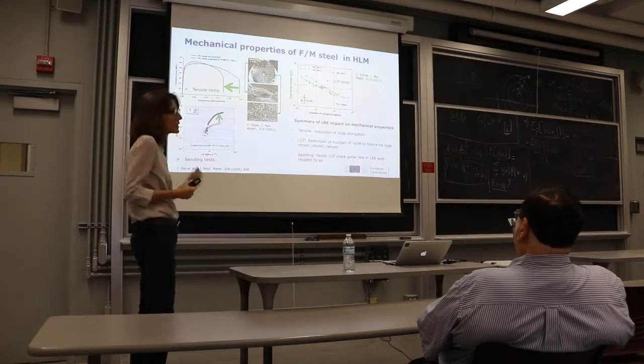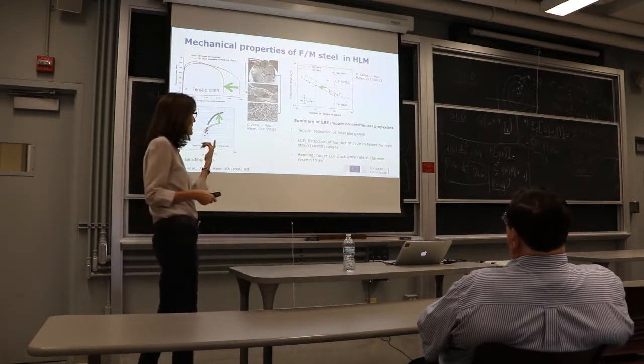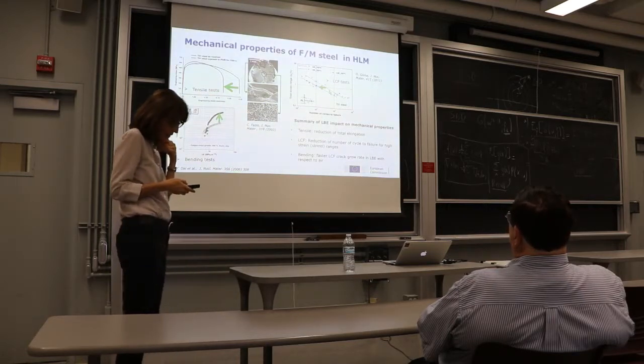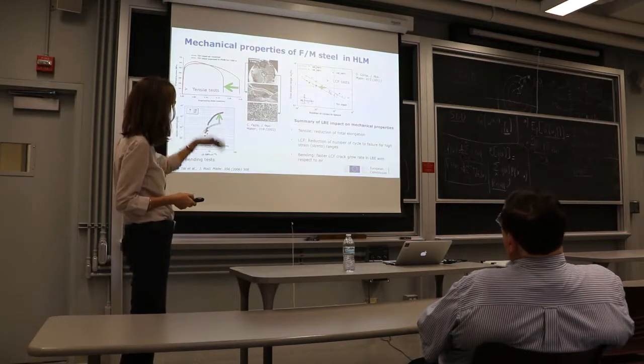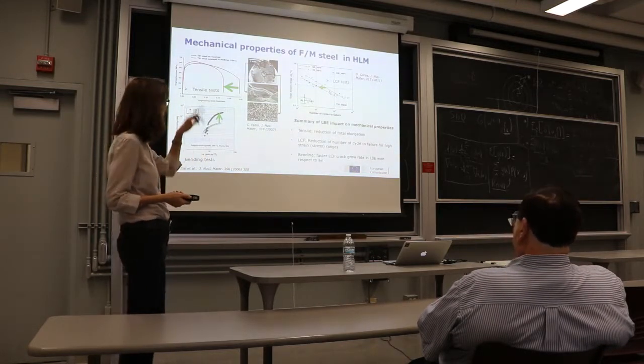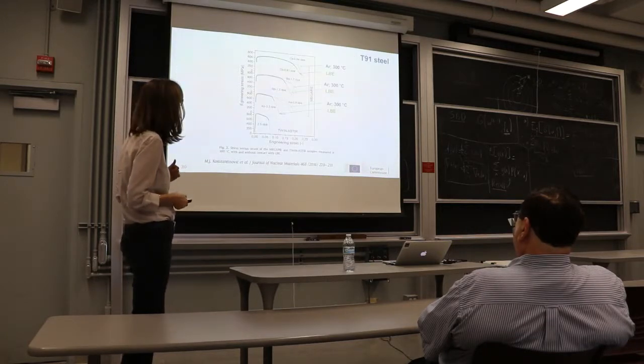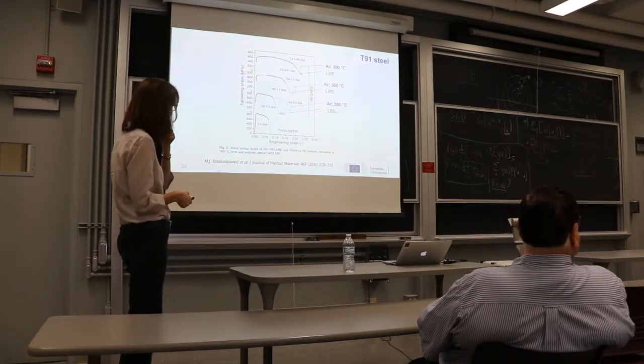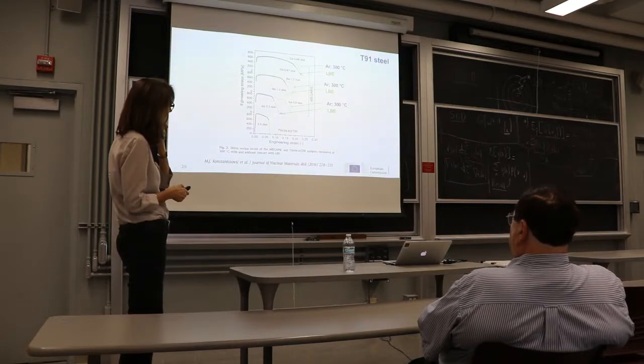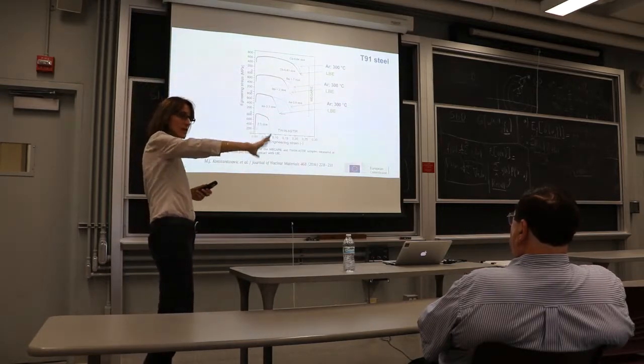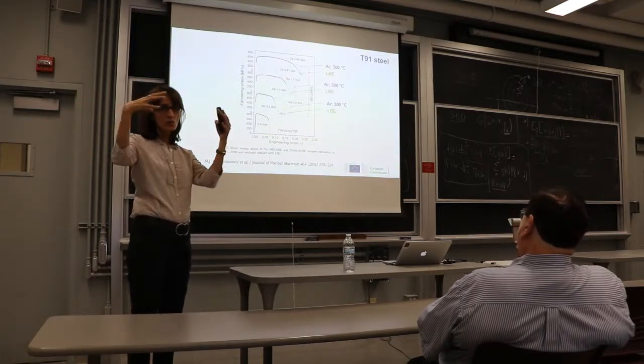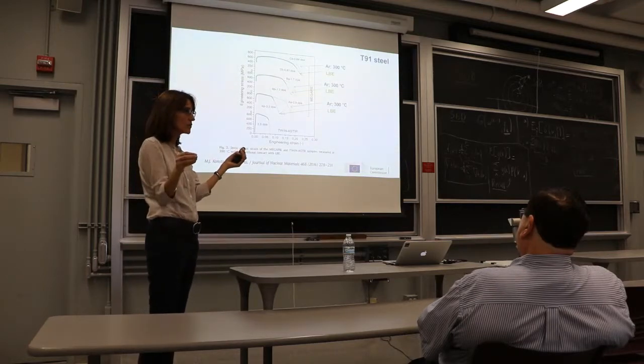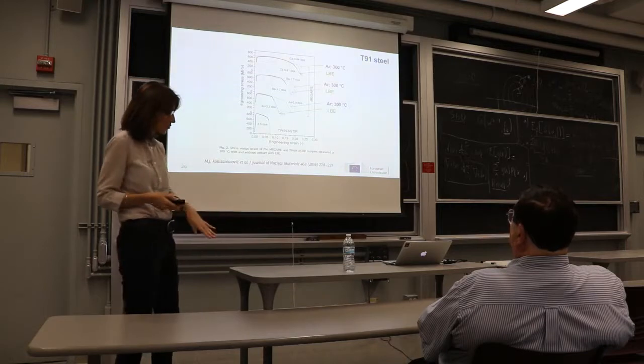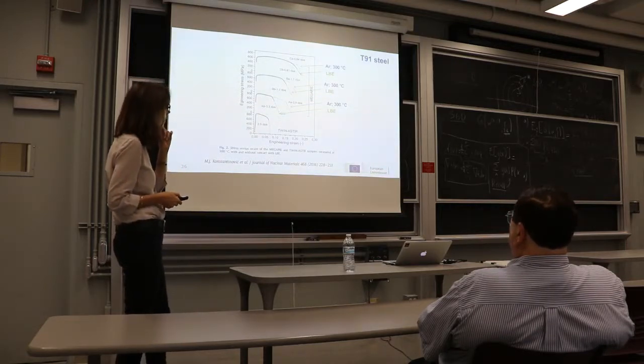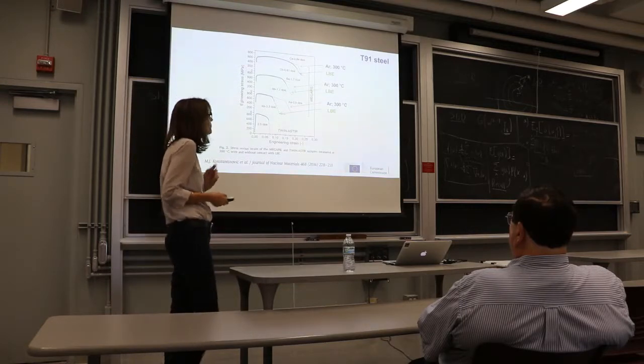And it's the same, so there are some low cycle fatigue tests, so the resistance of cycling, thermal cycling or mechanical cycling, is reduced in the liquid metal. So again, problems, and either one changes the steel, one tries to change the composition of the steel, or one designs the reactor around this type of problems. And this is more recent, it's 2016 results. So these are quite interesting results because we've seen that this ferritic martensitic steel has problems under irradiation, has problems in the liquid metal, but the two are synergistic. So in the moment that it's irradiated with liquid metal, the mechanical behavior of the material drops really a lot. So again, it's a question if this type of material is really to be used for the heavy liquid metal, question to be answered.